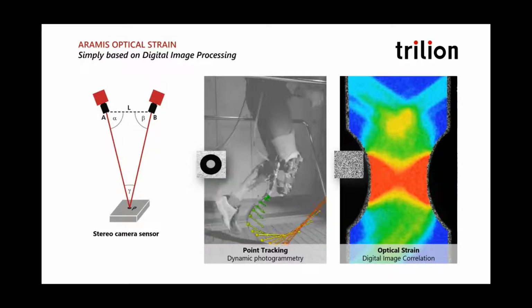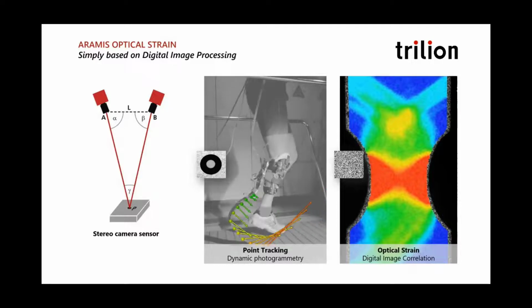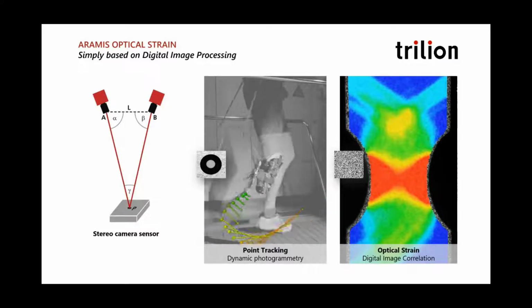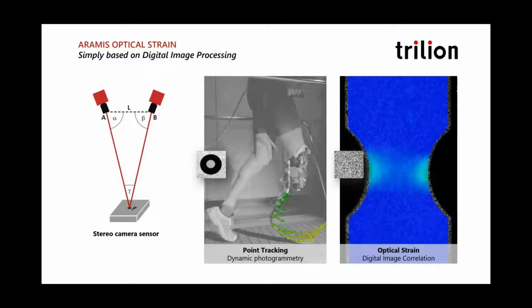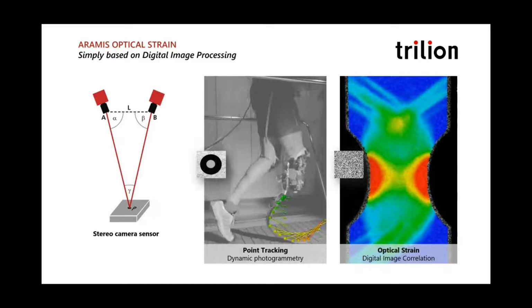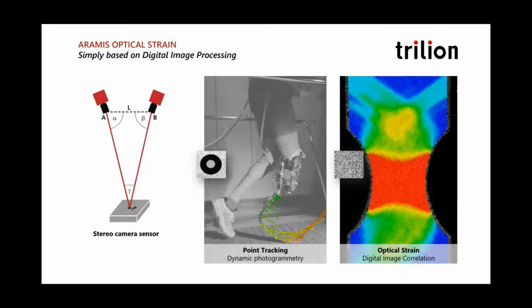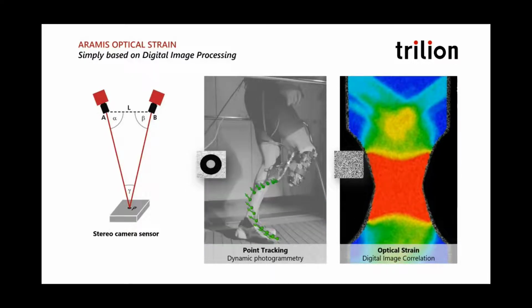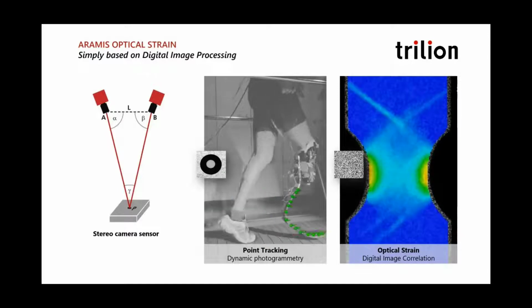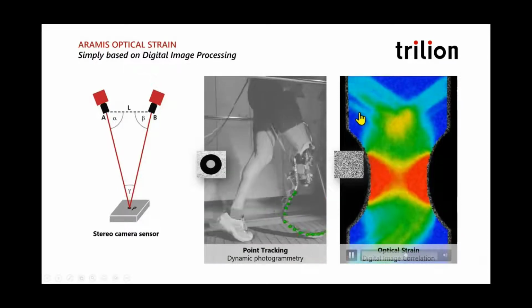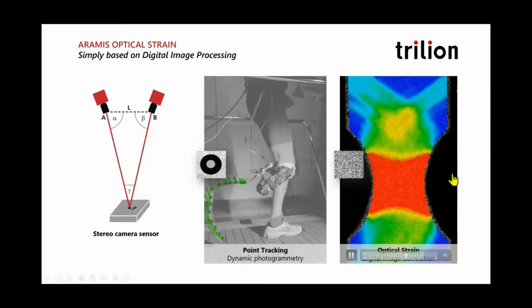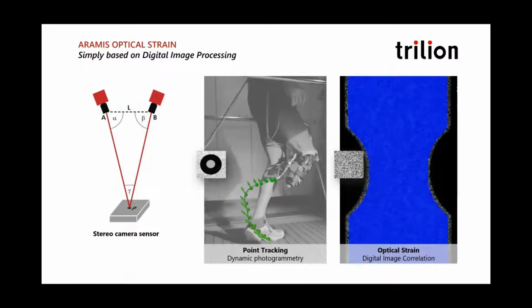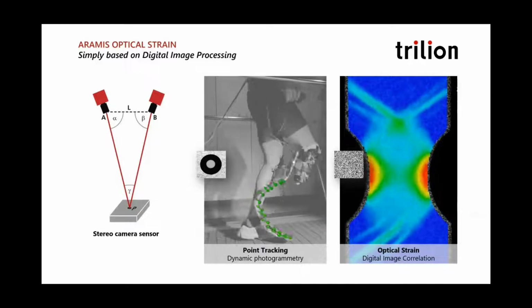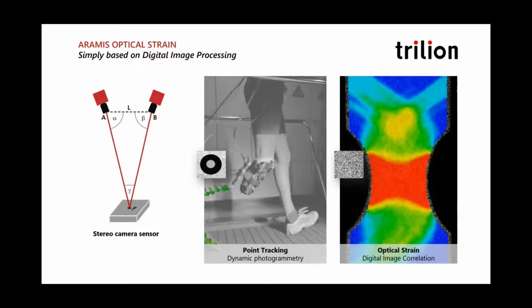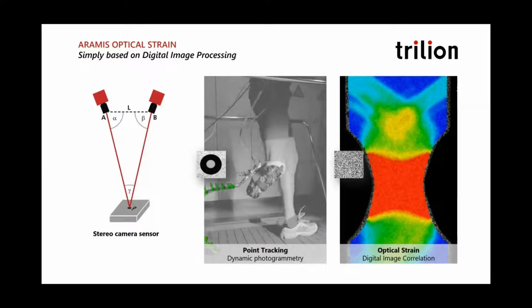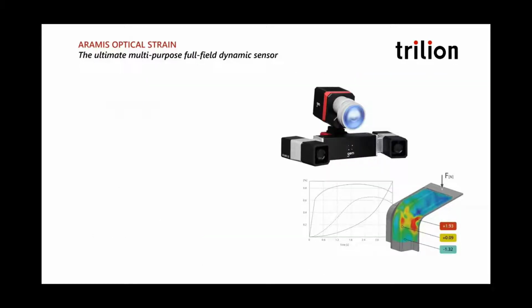We can also put a pattern down, and the pattern allows the software to create targets, continuous targets across the pattern. And this allows us then to see holistically what's going on to the structure. A clip gauge or a strain gauge is going to give you some average value. Here we have tremendous local resolution, to the extent that these Lüders bands up here are crystalline level response of this steel going through test. And so we're seeing right down to the crystalline level response of the material, far better than any strain gauge, clip gauge, or model can really calculate or measure.